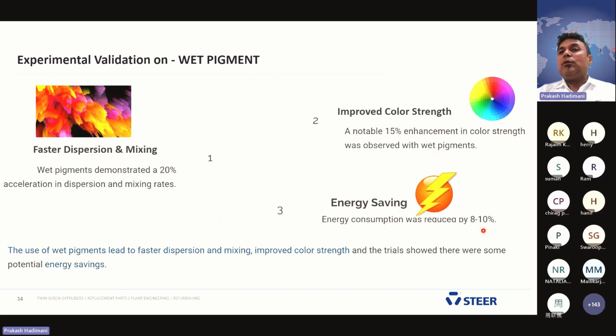And almost 8 to 10% energy saving compared to the dry pigment. When you use wet pigments, these are the advantages. Wet pigments lead to faster dispersion and better mixing, improved color strength, lower specific mechanical energy, and better distribution of the pigments in the polymer matrix.